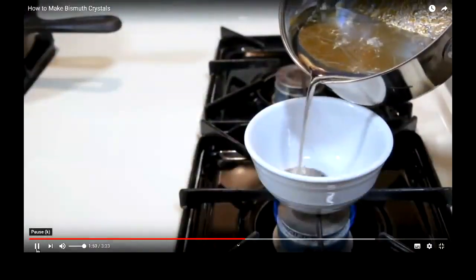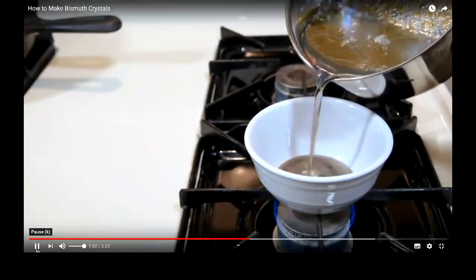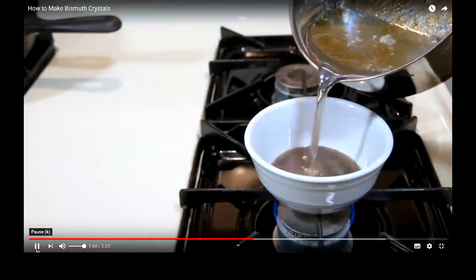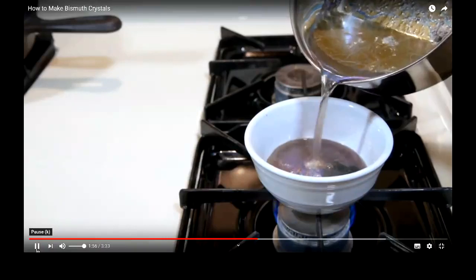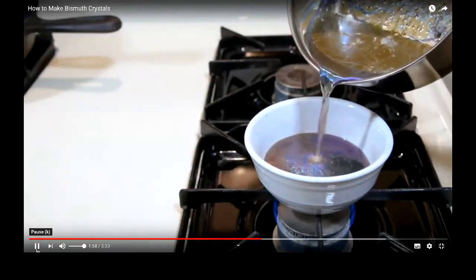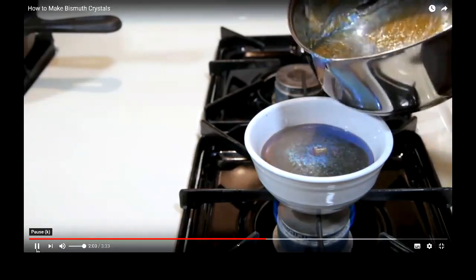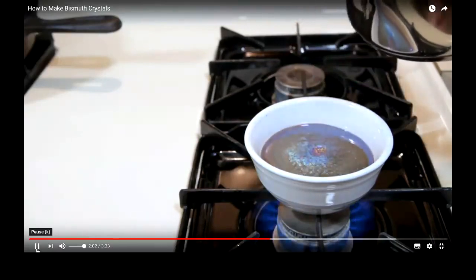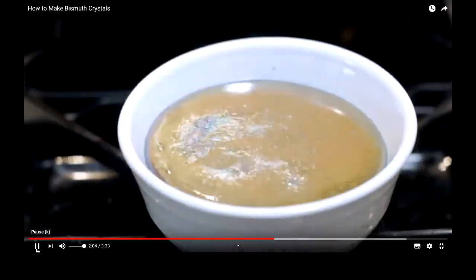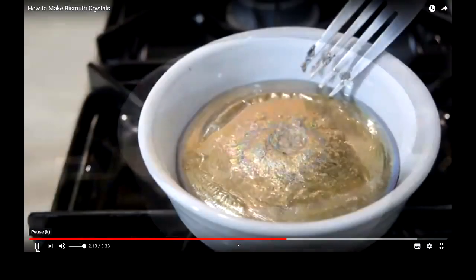A synthetic bismuth geode is also possible to create using a small ceramic bowl as a mold. The ceramic needs to be preheated so it doesn't crack from temperature shock when the bismuth is poured in. This particular process has a high potential for spills, so it's much more dangerous than making surface layer crystals with the previous method. Don't try this one at home.